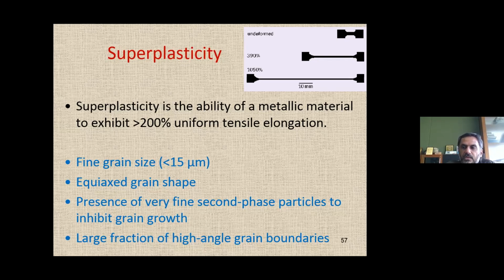Please understand, we are talking about plain FSP. We are not adding any reinforcement. When you take a tool and just run it through the aluminum plate, depending on your process parameters, you may get fine grain structure, equiaxed grain shape, very fine second phase particles, and large angle grain boundaries. These are the attributes which are required to get uniform elongation, right? If the elongation is more than 200%, the material is considered to have superplasticity. So that is also achieved with the help of the FSW tool.